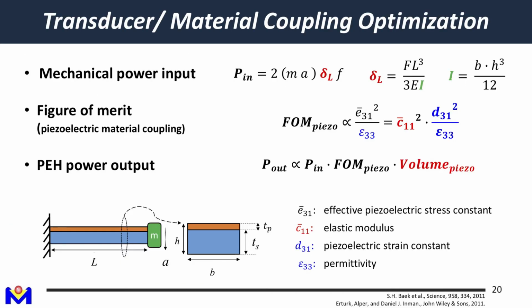Okay, so if we want to do further simplification to see more theories, we can have an even simpler model. Forget about the microcantilever beam. Here we have a very simple model. This is a base excitation. So it's equivalent to having an external force to move this proof mass. With a cantilever beam, the work done by the proof mass will be like here: the mass of the proof mass times the acceleration times the tip displacement times 2, because per cycle you have force forward and back, so 2 times the work done. And when we multiply the work done by the frequency, you actually get the mechanical power.